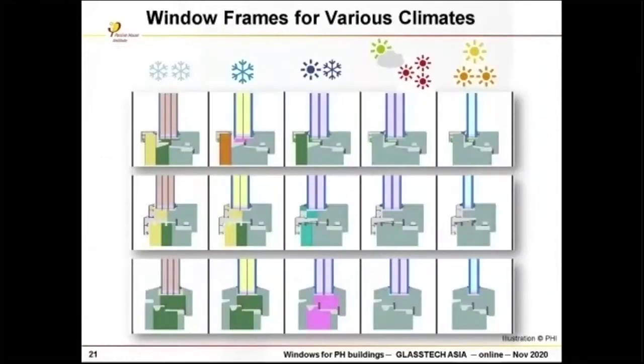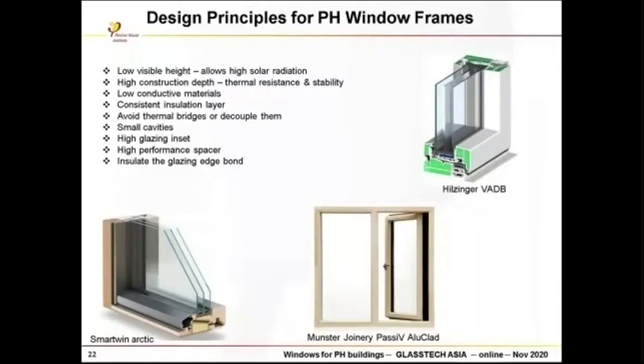Well, and if you have this all together, just an overview for 3 types of frames. You see here for a very cold climate, and for the warmer climate, here you have almost no insulation, just wood. But for the colder climate, you have to check and get better insulation, here an extra shell, so that your window frame U value is as good as possible. Okay, here as a summary, the 2 window frames you see here, a very slim width at the side of the window frame is desirable, so that the solar throughput through the window is as good as possible always.